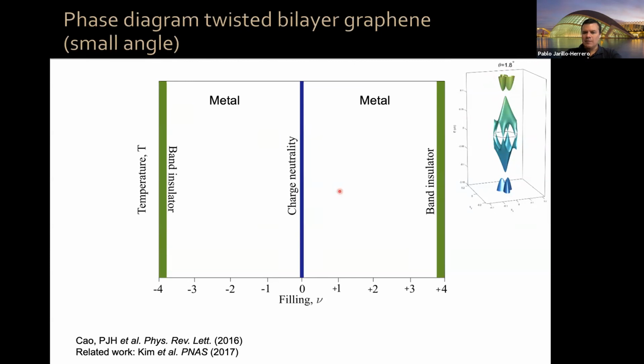Therefore, in this phase diagram now, besides charge neutrality, because of these graphene-like Dirac cones, you also have band insulators when your chemical potential is here or here. And that occurs at 4 electrons or 4 holes per Moire unit cell. Remember that we use this thing called filling factor, nu, to represent in a Moire superlattice the number of electrons or holes that you place per Moire unit cell in these central Moire mini bands, whether it's a flat band or like here, these flattish Moire mini bands, you can put 8 electrons per Moire unit cell in total, okay?